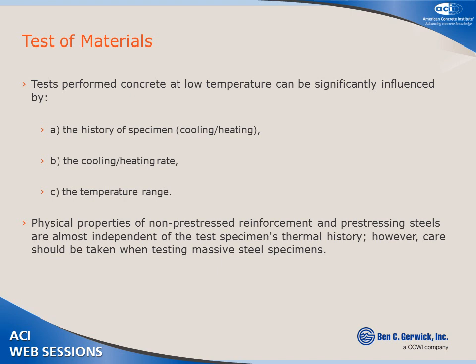The history of the specimen — the cooling and heating — can become important because it can influence the moisture content of the concrete. Moisture in concrete can influence cyclic fatigue properties, permeability, heat of hydration, thermal conductivity, and specific heat properties. So it is important to understand the history of the specimen not only in service but also during construction. Additionally, the rate at which you heat and cool can influence thermal gradients through the walls, affecting the crack history of the structure.